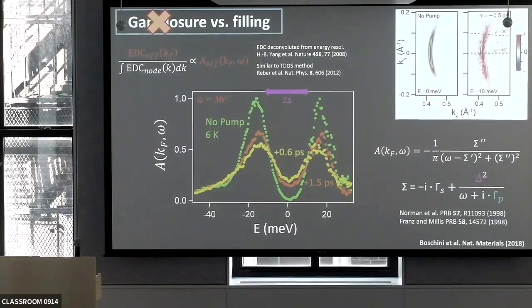Okay, but wait, what I see in this experiment is that the consequence of the pump is a filling in of the density of states with only a very small change in the gap. Correct, yeah. But is there any independent information about the effect of the pump on superconductivity? Well, if you're asking transport type, no. Basically there is not. Fabio can go on increasing the fluence until you can no longer see a gap. And this is a question that I will address with the last two slides of the talk, because really the question is, what kind of experiment can you do on these kinds of time scales where you could probe that?